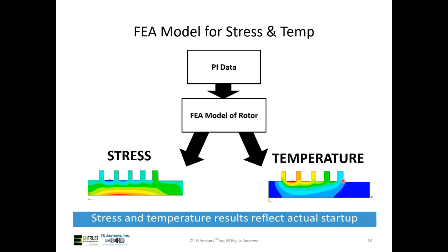So just quickly, what I said verbally: we call it PI data because that's what most folks use, but operational data is exported from a real turbine startup from your unit, we make a finite element analysis model of the rotor, and we can simulate the startup on the computer. We can simulate changes, and what we're looking at is stresses throughout startup, particularly on that center line or bore surface, and temperature throughout startup. With temperature, we can figure out material properties throughout startup. Remember, one of the first things I said is that the material properties for the high temperature rotors change throughout the startup. It starts brittle and transitions to ductile behavior. So we have to incorporate that knowledge as well.